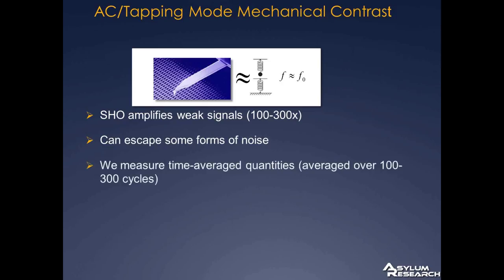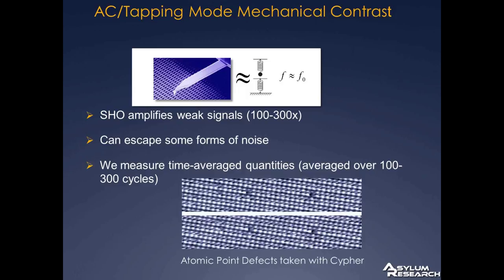So when we do that, we're basically measuring the effects of the tip-sample interaction averaged over some number of cycles as the tip taps on the surface. That built-in time averaging is what helps us have such spectacular signal-to-noise. One of my favorite examples is an image like this, taken on the Cypher, where you can see a frame up and a frame down of an AC mode, tapping mode image of single atomic defects in a calcite crystal surface. The signal-to-noise on this is quite spectacular. It's very difficult to do with any other sort of technique.